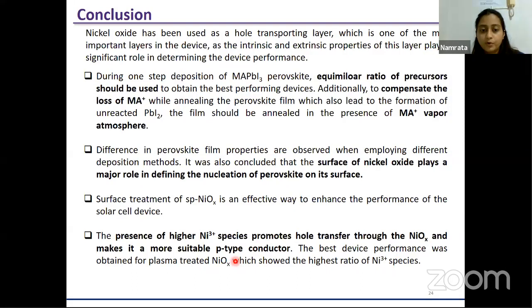And of course, the presence of nickel 3+ species promotes hole transfer through the nickel oxide and makes it a more suitable p-type conductor, as we could see that the Ni3+ to Ni2+ ratio was the highest for the plasma case. So of course, the ratio is never fixed, but we definitely need a higher Ni3+ as compared to Ni2+. So this makes it a more suitable p-type conductor, and the best performance was obtained for plasma treated. As I said, we have the highest ratio for Ni3+ species.